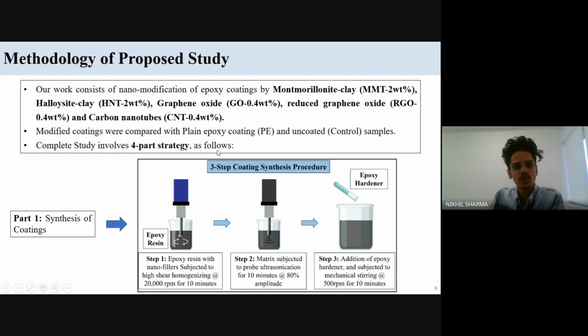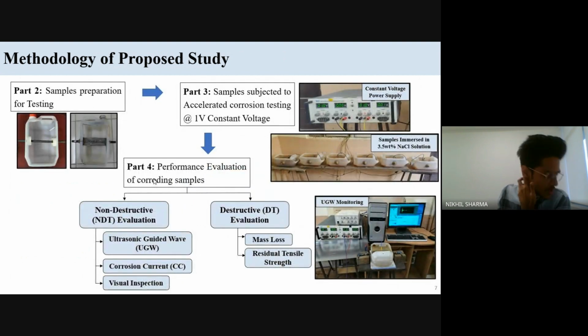Our complete study involves a 4-part strategy, in which part 1 includes the synthesis of these nanomodified epoxy coatings. In the synthesis, we add the nanofiller to the epoxy resin and subject it to a high shear homogenizer at 20,000 rpm for 10 minutes. Then it is subjected to probe ultrasonication for 10 minutes. After that, we add the hardener and subject it to mechanical stirring for 10 minutes, and the coating matrix is ready and applied to the rebars. Then in part 2, we prepare the sample for corrosion testing.